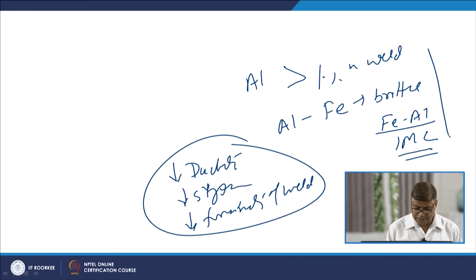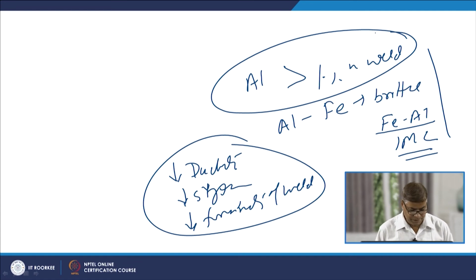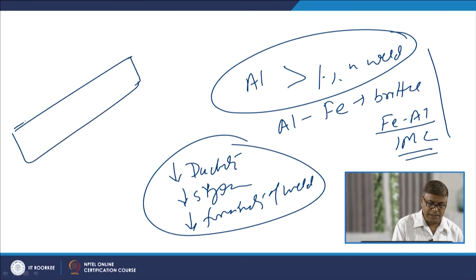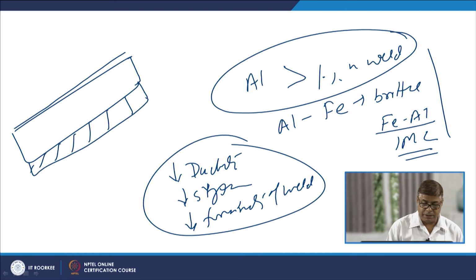So, the greater the thickness of the sheet, the lesser will be the weight percentage of the aluminum in the weld metal. On the other hand, if the coating thickness is greater, the thicker aluminum coating will lead to a greater percentage of aluminum in the weld metal, and that will be more troublesome as far as the reduction in ductility and formability is concerned.